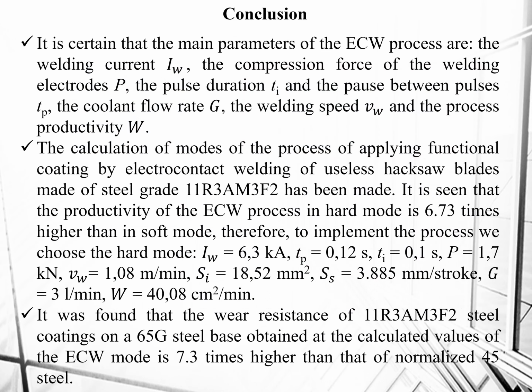It is certain that the main parameters of the ECW process are the welding current, the compression force of the welding electrodes, the pulse duration and the pause between pulses, the coolant flow rate, the welding speed and the process productivity. The calculation of modes of the process of applying functional coating by electrocontact welding of useless hacksaw blades made of steel grade 11R3AM3F2 has been made. It is seen that the productivity of the ECW process in hard mode is 6.73 times higher than in soft mode. Therefore, to implement the process we choose the hard mode.